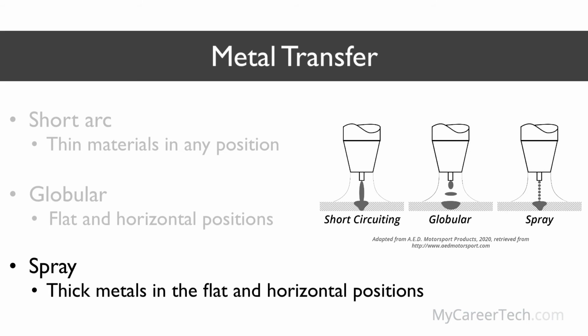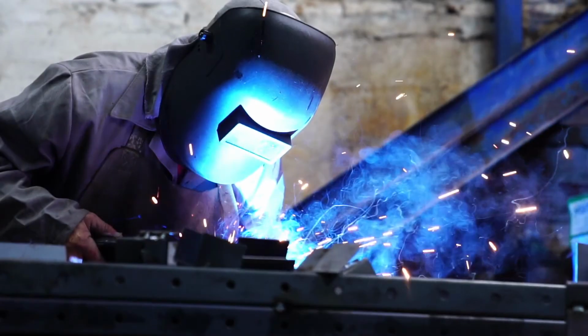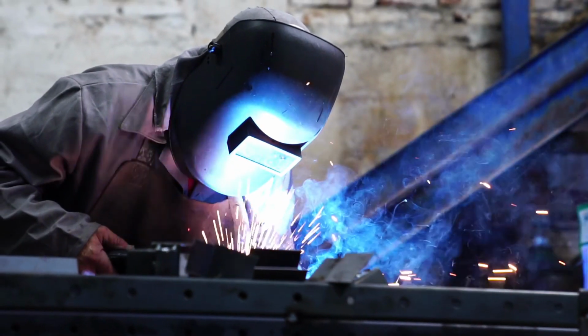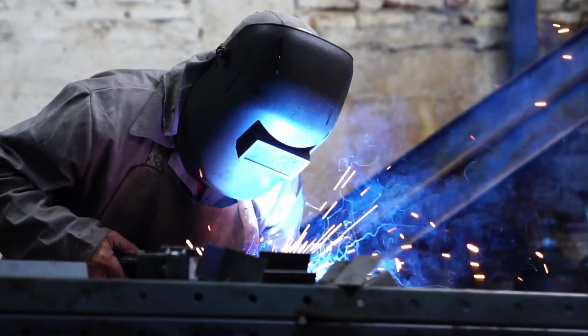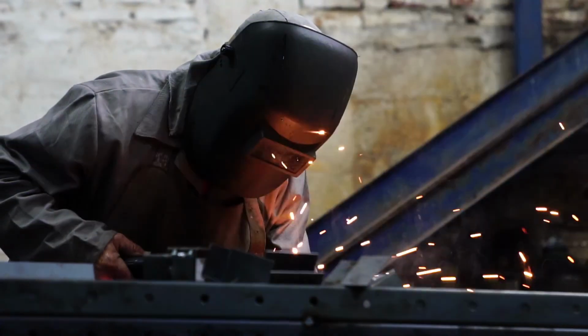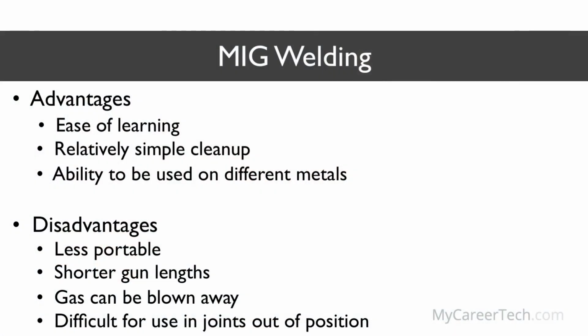A spray transfer occurs when the small molten droplets are detached or sprayed across the arc towards the weld pool by electromagnetic forces. This method produces very little spatter and is most often used on thick metals in the flat and horizontal positions. There are many advantages to the MIG welding process, including but not limited to the ease of learning the procedure, relatively simple cleanup depending upon the materials used, and its ability to be used on different metals. Drawbacks include the fact it's less portable, with shorter gun lengths, the gas can be blown away by high winds, and it's difficult to use in joints that are out of position.